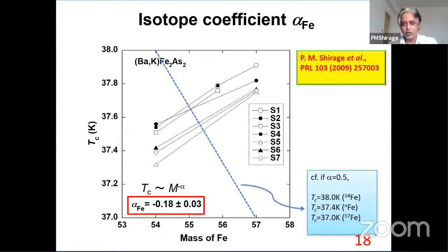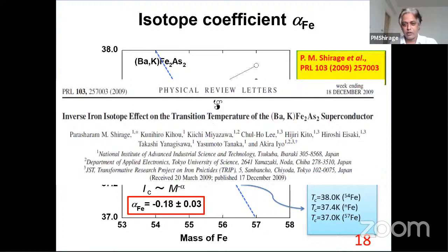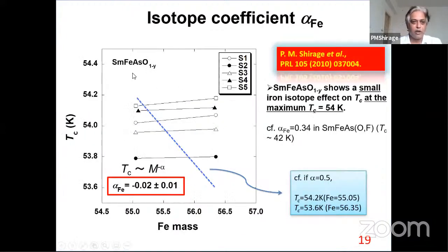Another important contribution which I made is this 1111 superconductor. Earlier it was the 122 superconductor; this is the 1111 superconductor, samarium iron arsenide oxygen. And in this, the interesting result we found is that if we change the isotopic mass, there is no change in the TC. Basically, these studies lead to an understanding of the mechanism of superconductivity. Why are they superconductors? What is the mechanism: electron-phonon interaction, electron-spin interaction, or spin-orbital interaction? We can get all this information from this, and that's why this is also published in Physical Review Letters.